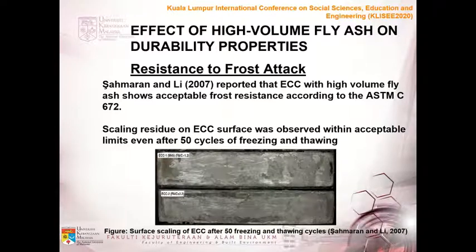Okay, then resistance to frost attack. Sahmaran and Lee in 2007 reported that ECC with high volume fly ash shows acceptable frost resistance according to ASTM C672. The scaling residue on the ECC surface was observed within acceptable limits even after 50 cycles of freezing and thawing. And this is the picture showing the surface scaling of ECC after 50 freezing and thawing cycles.